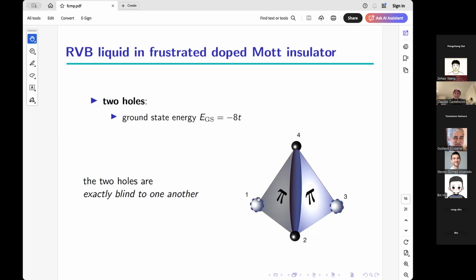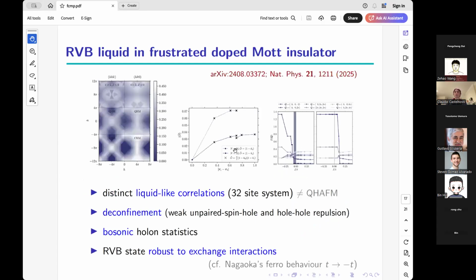So in principle, you would expect some excluded volume corrections, because 1, 3 is not a hopping channel, but in this system it is perfectly destroyed by destructive interference. And so they really don't see one another and don't affect one another in any way, and it's minus 8t the energy. Of course, this beauty, this elegance stops at 2 holes. If you have 3 holes, well, they begin to see one another because they no longer afford this perfect destructive interference. But generally we see numerically, and we generally expect, some kind of few-body scattering corrections to the picture when you go to finite hole density, and the wave function is no longer writable with paper and pen, or at least not that we have found so far.